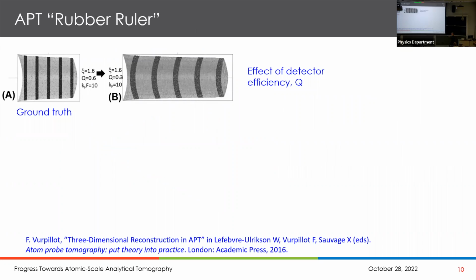But for all the beauty of that kind of image, there are some detractions, and this is the most serious one. In the atom probe, we don't have a high spatial fidelity in general. And this is illustrated very nicely by some work by Francois Vurpillot, who created a specimen in a computer. So he knows the identity and position of every atom in that image. And then he goes through a standard reconstruction using the protocols that have been developed for atom probe tomography. I won't go into those, it's a lot of geometric stuff, but it has to do with the compression of the electric field as the ions fly away. But Q here is the detection efficiency. Typically, it used to be 60%, now it's about 80%, not 30%.